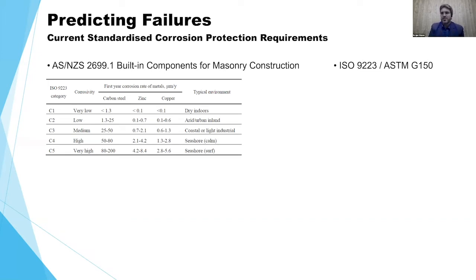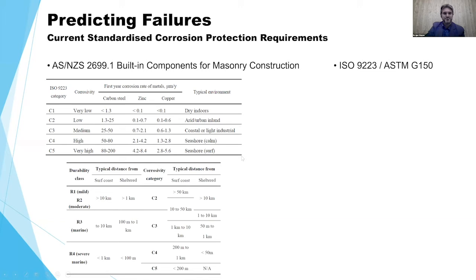So we have, in this case, for the Australian categories, 5 different levels of aggressiveness, C1 to C5, as you can see here. It subjectively classifies the corrosivity from very low to very high, and it gives you an indication of the corrosion rate per metal, okay? Typical environment examples are also given here. Once the exposure classification is defined, and this is done by a mapping zone, it's as simple as looking at where you're going to build. That's your category.